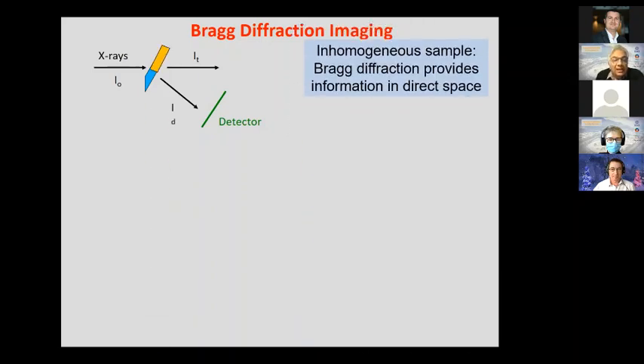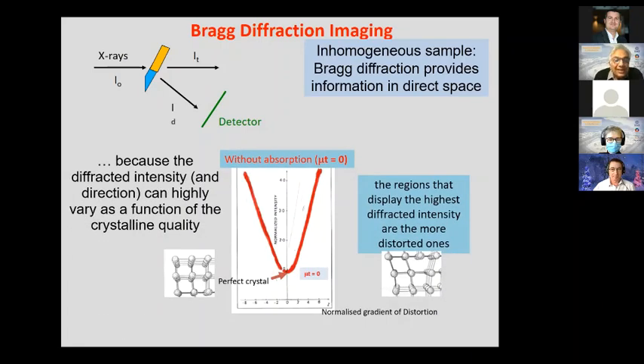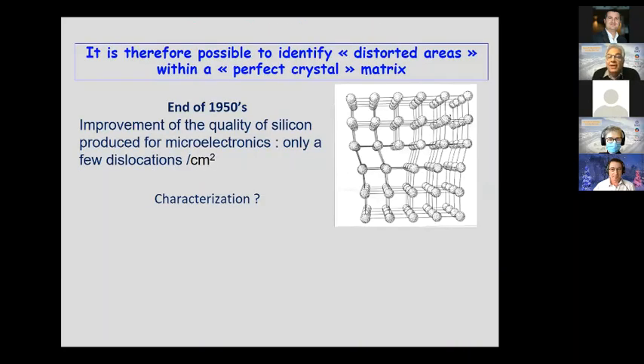If your crystal is inhomogeneous, Bragg diffraction provides information in direct space, because the diffracted intensity and direction of the diffracted beam can vary strongly as a function of the crystalline quality. I show here a curve for no absorption, and this curve represents the integrated diffracted intensity as a function of the distortion of the sample. You see that there is a minimum for the perfect crystal with no distortion, and that it goes up for distorted crystals. That is, in the low absorption case, the regions that display the highest diffracted intensity are the more distorted ones. It is therefore possible to identify distorted areas within a perfect crystal matrix because they diffract differently.